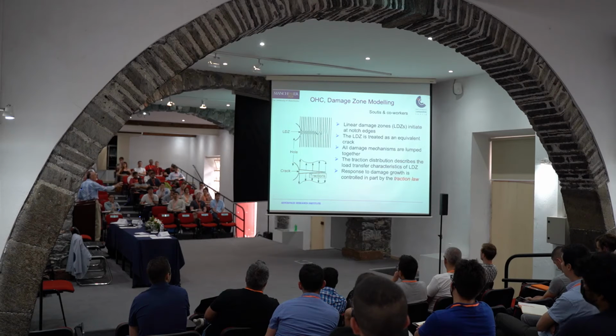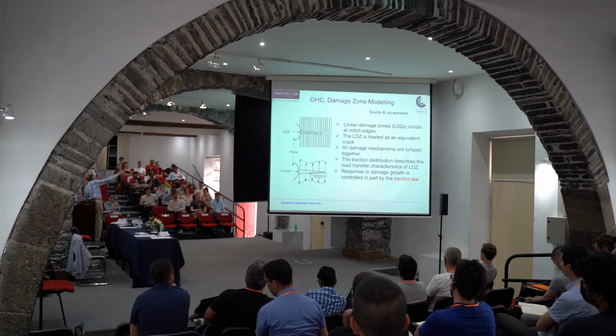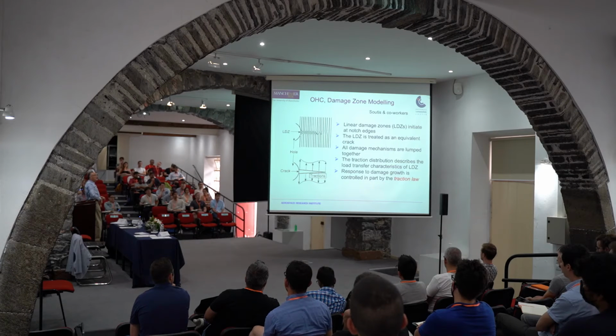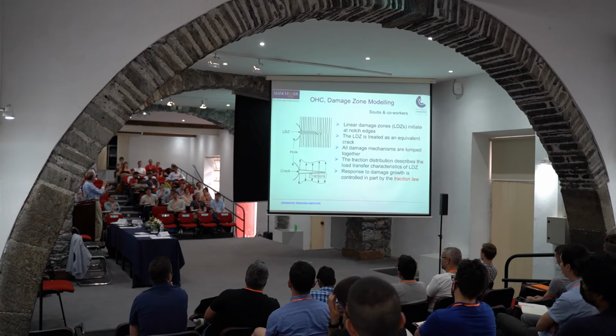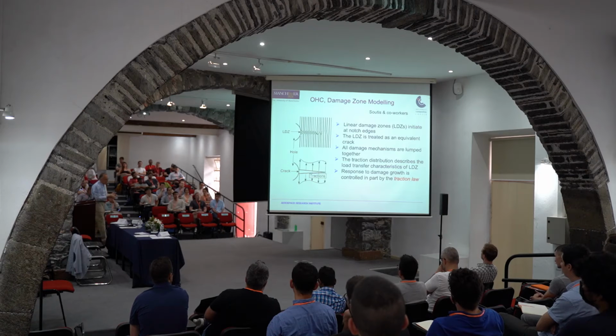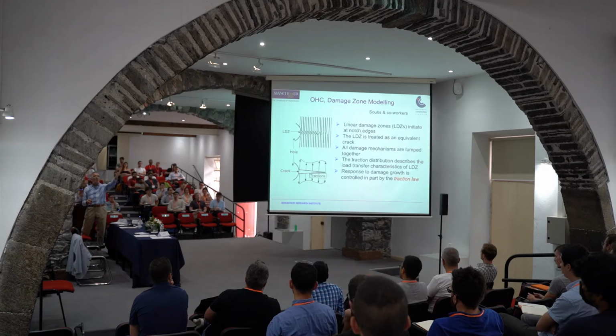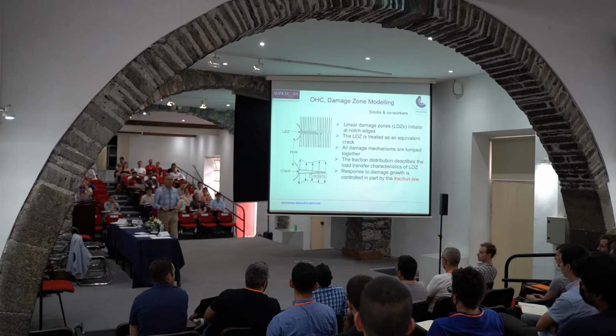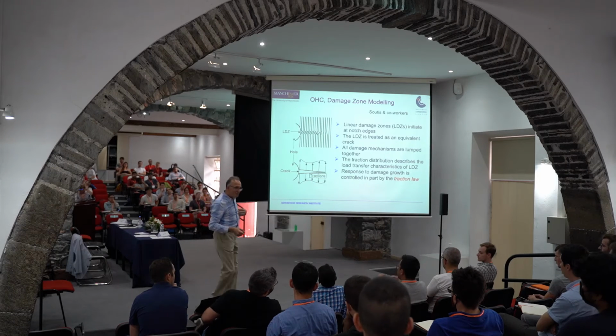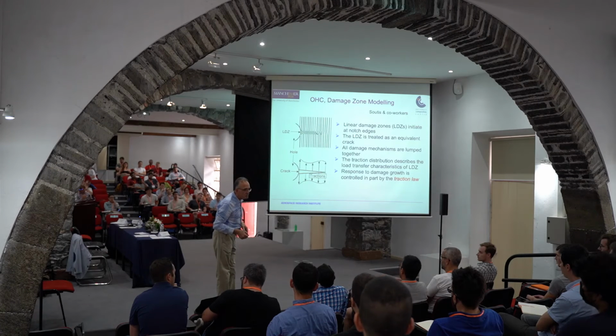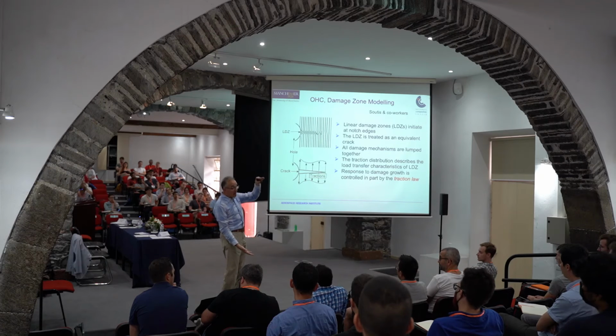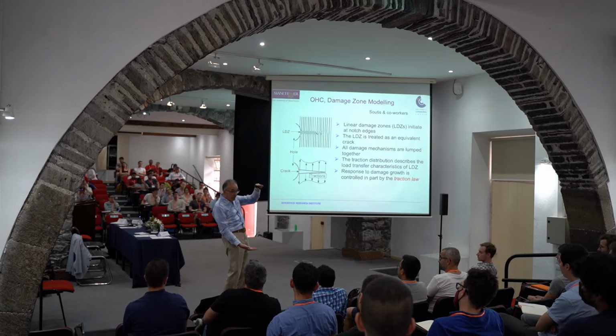So I replaced that damage zone with a linear damage zone that initiates at the notch, at the edge of the hole. And of course, I apply compressive loading, but the fibers that we try to buckle, that we try to break, provide resistance, and that's the traction distribution that describes the load transfer characteristics of this local damage zone, which will dictate how successfully you estimate the overall compressive strength. Yes? Where did you see this crack, in which ply is it seen clearly? In the zero ply. Okay. Because you remember, the main stress component is axial compression.